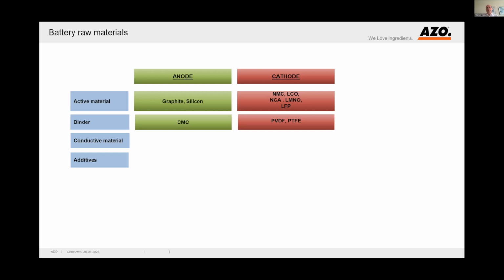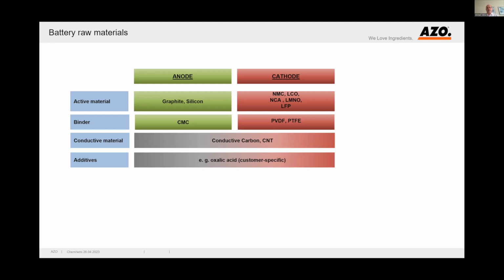If we have a look in the future, for example, for dry mixing and dry coating processes, the PVDF, for example, is replaced by PTFE binder, which has some special characteristics. The conductive material is always conductive carbon and quite often carbon nanotubes also. These carbon nanotubes are sometimes added as a powder or already prepared in a slurry and added to the mixer. There are few additives. Typically one is oxalic acid, but this is not used in every factory.